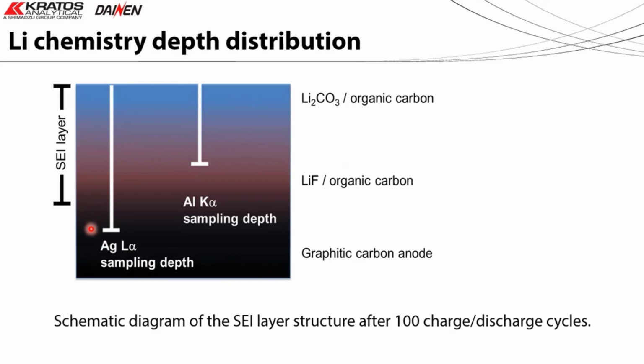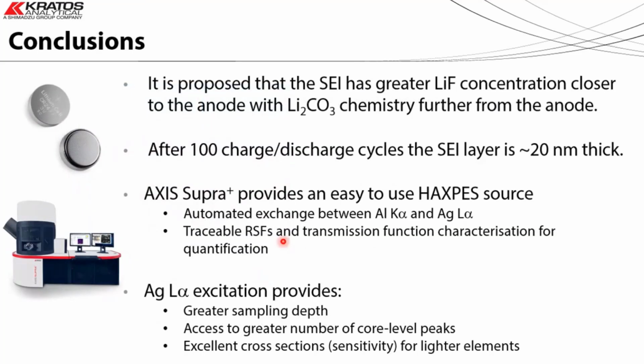anode, and we're estimating that the SEI layer is probably around about the same sampling depth as we would expect for the silver excited carbon 1s, which is about 19 nanometers. So in conclusion, the SEI layer has a greater lithium concentration closer to the anode, with the lithium carbonate, which is probably a result of degradation products from the cathode migrating to the anode and reacting with the lithium to form a carbonate species. The SEI layer after the 100 cycles is about 20 nanometers thick.